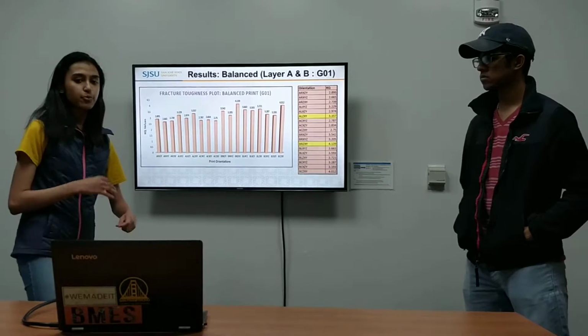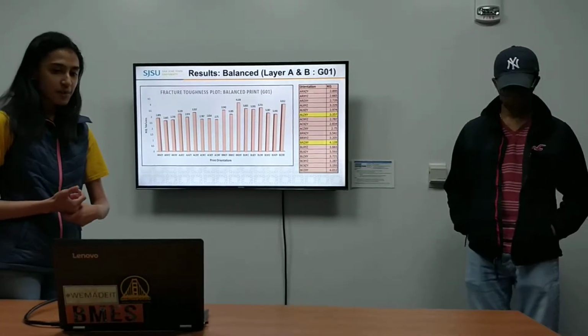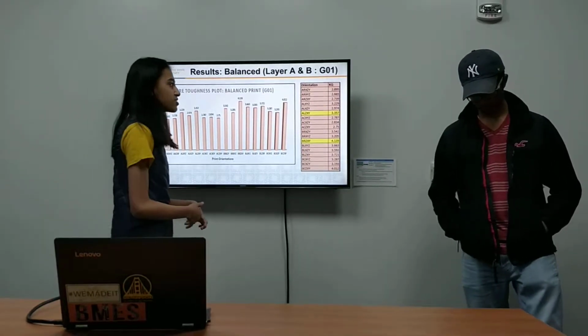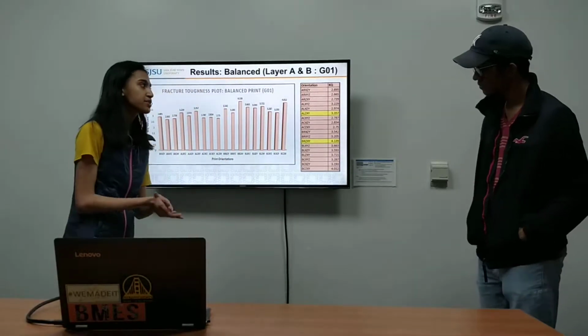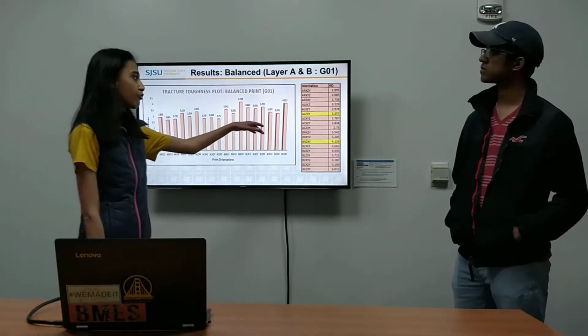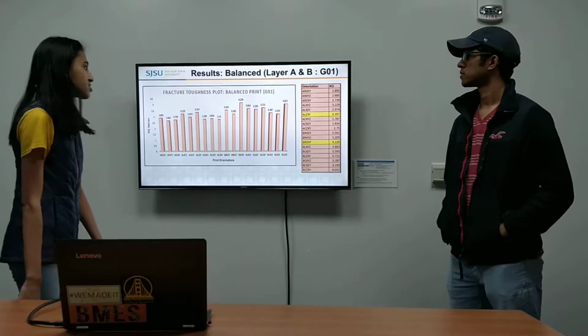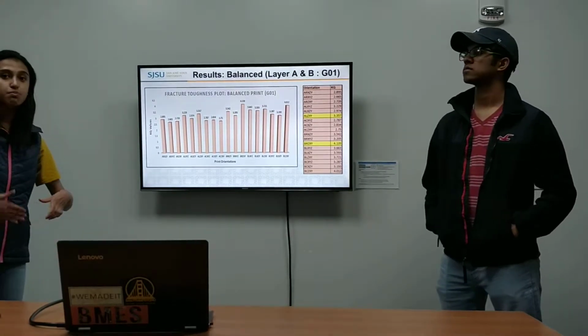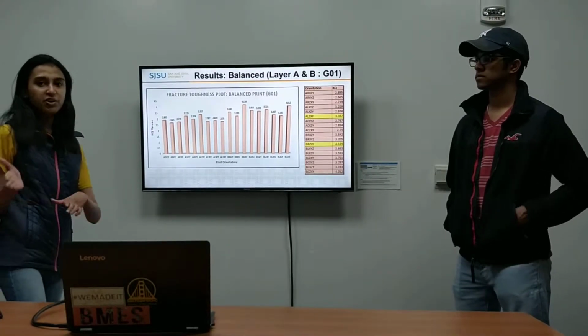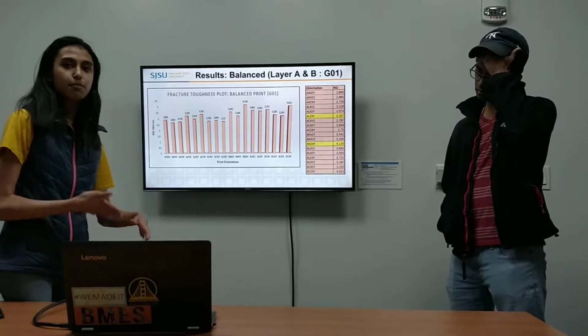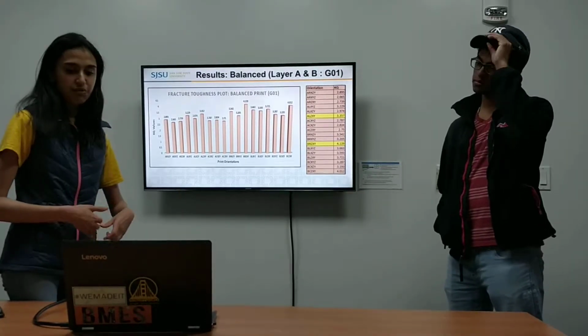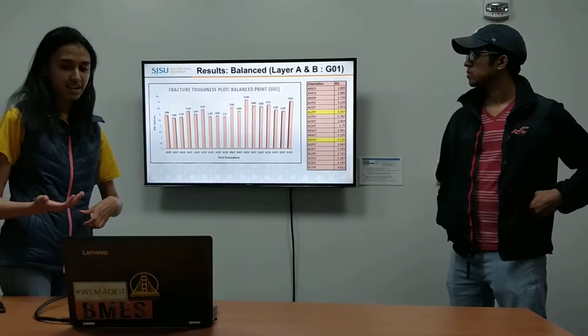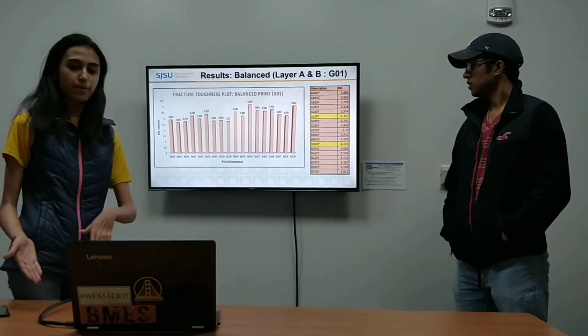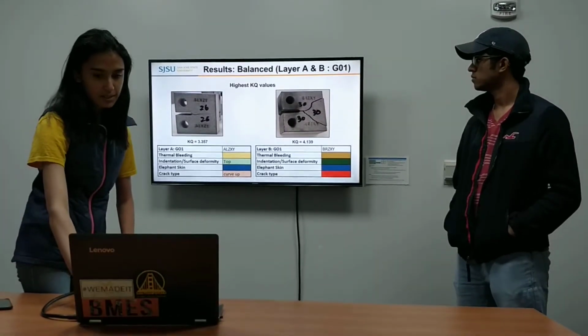And this is for another print setting, which is balanced. So for balanced, we again found that ZXY produced the highest fracture toughness for both A and B layers. So this confirms our results more and more that we are on the right track, and it complies again with the literature review which we studied before conducting our experiments, that ZXY produces the highest fracture toughness.